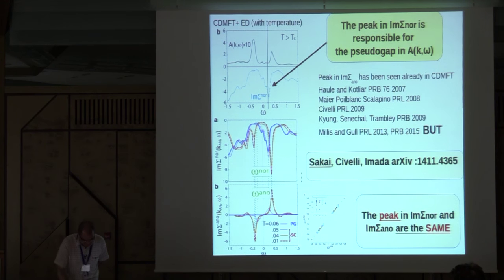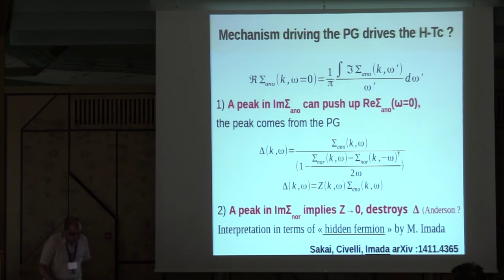And this is the last slide I have. Just to say, this is work in progress. Actually, we have a preprint already out if you want to look in more detail. A peak in imaginary sigma means a push-up of the gap. This peak is actually the same that is creating the pseudogap. So in some sense, the pseudogap and superconductivity look like they are competing for the same electrons. But on the other hand, the presence of the peak in the self-energy, so the presence of the pseudogap, is shaping the anomalous self-energy, and this can boost up Tc.